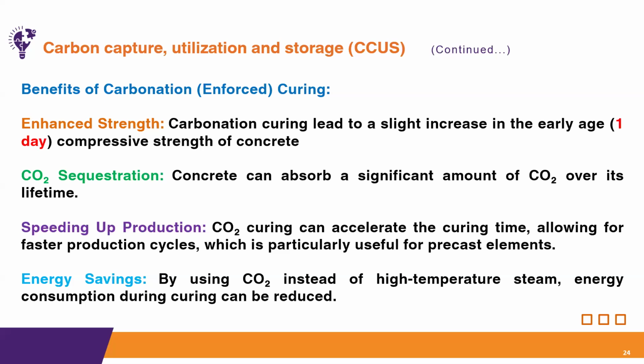Also, another benefit is the speeding up of production. Carbon curing can accelerate the curing time, allowing a faster production cycle, which is particularly useful for precast elements. In precast, like blocks and other panels, we can reduce the curing time by using this technique. And also the energy saving. Normally in the precast industry, high temperature curing is used. So instead of using high temperature curing, if we use carbon curing, we can reduce a lot of energy consumption this way.